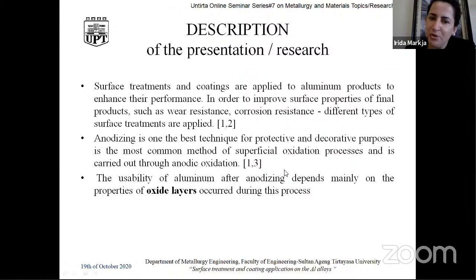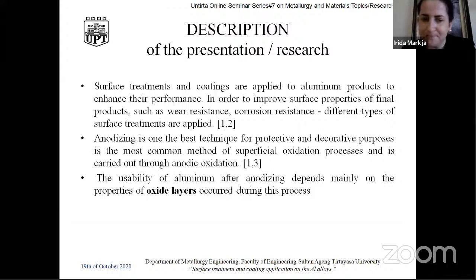It is one of the common methods for superficial oxidation processes, and it is carried out through anodic oxidation. It's a chemical reaction on the surface of aluminum products, which creates the oxide layers. And the usability of aluminum products and aluminum alloys after anodizing, as a chemical treatment on the surface, depends on the properties that the oxide layer has after this process, because it depends on the added components, or the chemical composition, of the aluminum alloys.